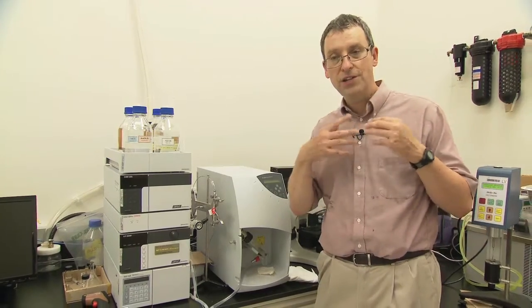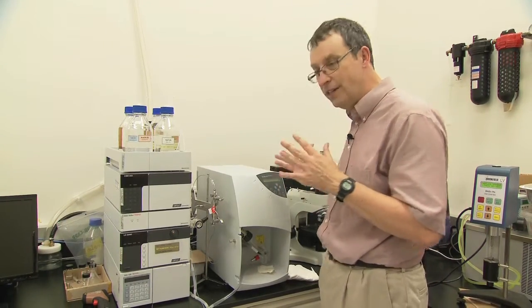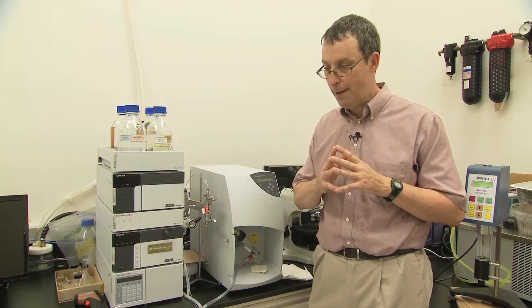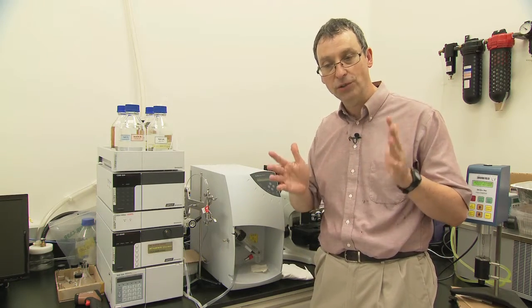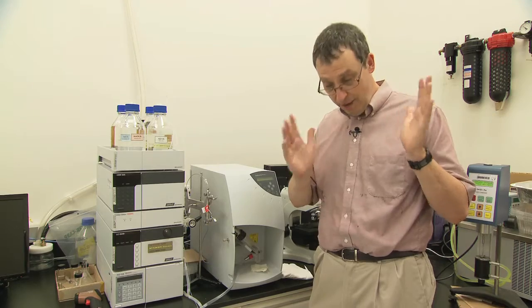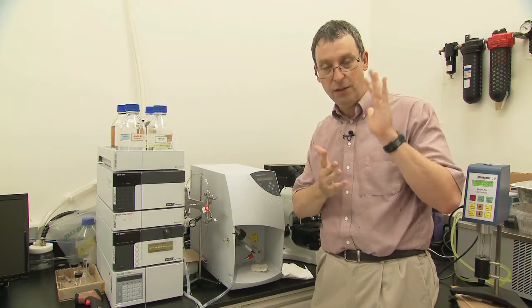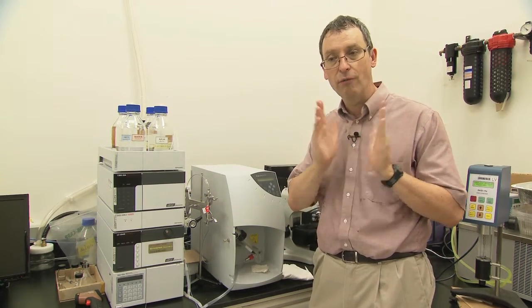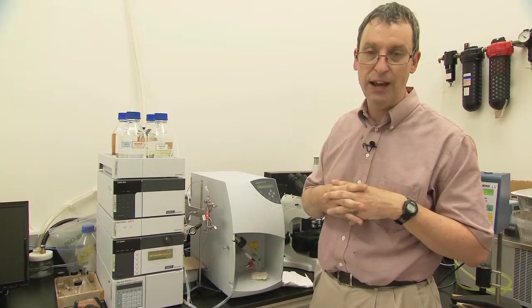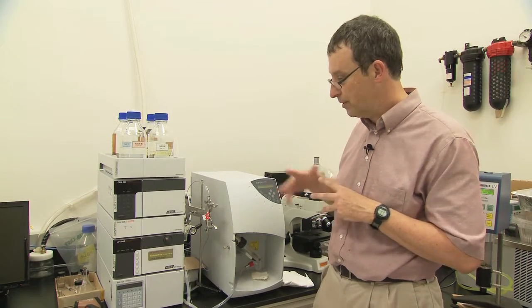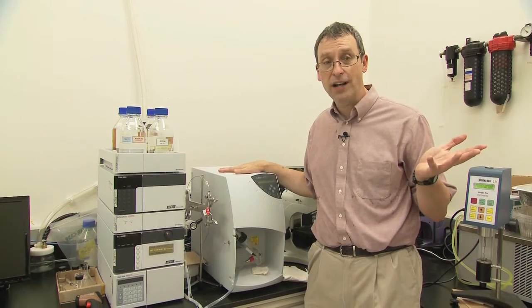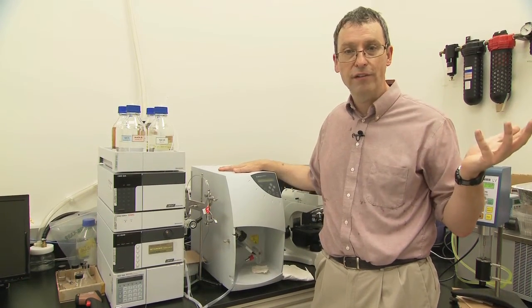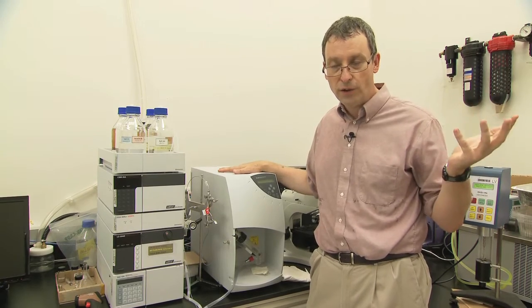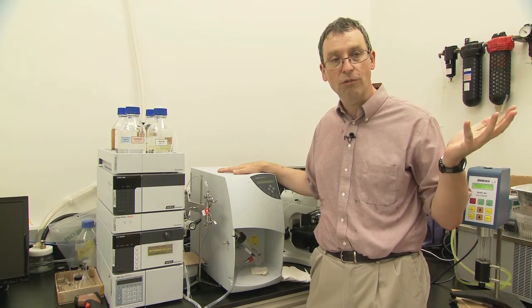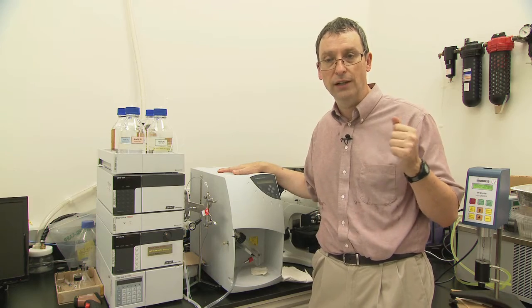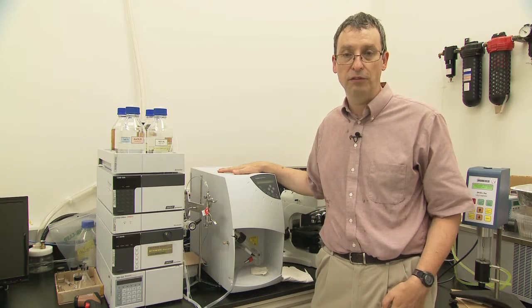It goes through this separation column, and then it goes through our detector, which indicates the presence of the molecules as peaks. And we measure either the area of the peak or the height of the peak, and again use that as a ratio of one peak versus the other, and that ensures that we have the proper mix ratio of our resin. So that is the equipment we have in our chemistry lab. Again, they're all very effective tools for measuring not only quality control of our process and our raw ingredients, but also helps us to develop new resin systems for maybe future core.